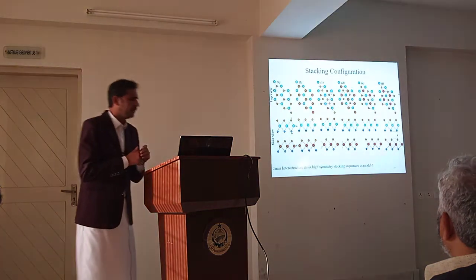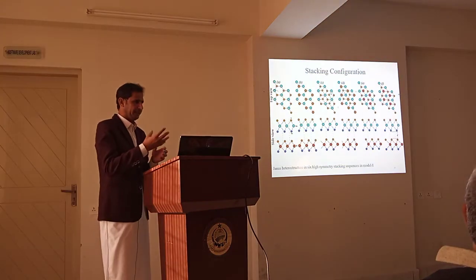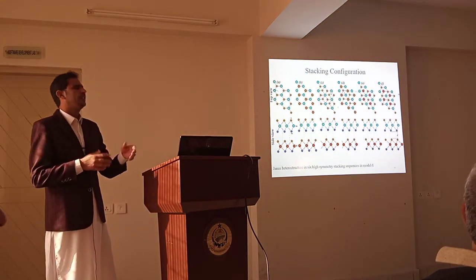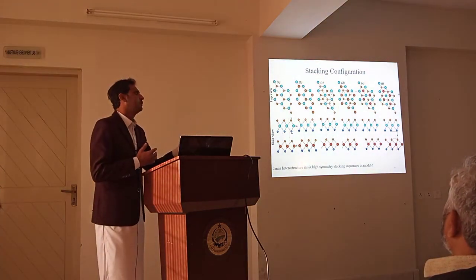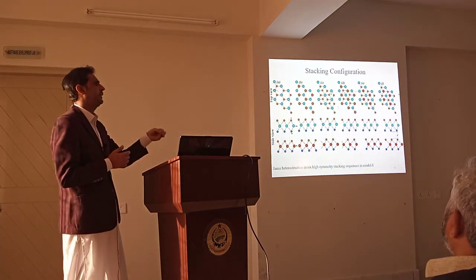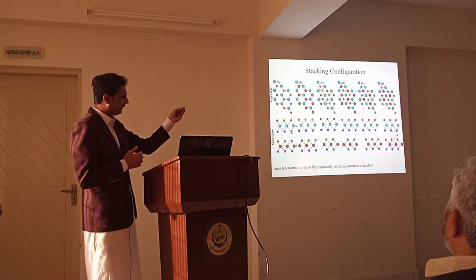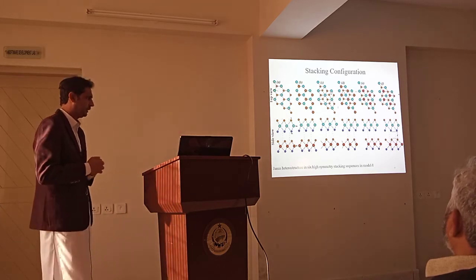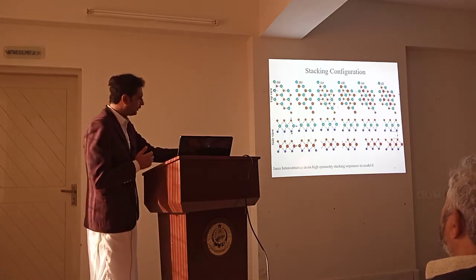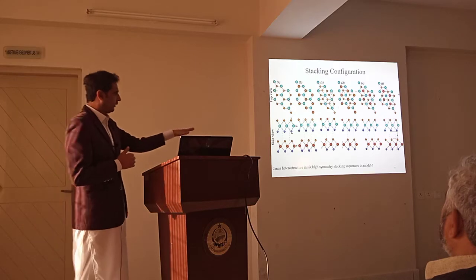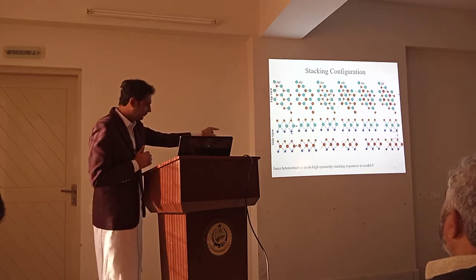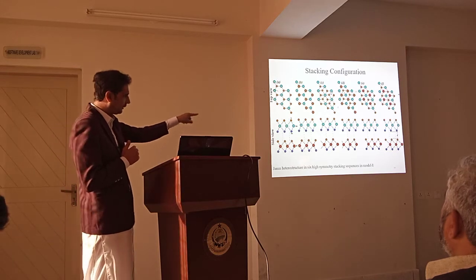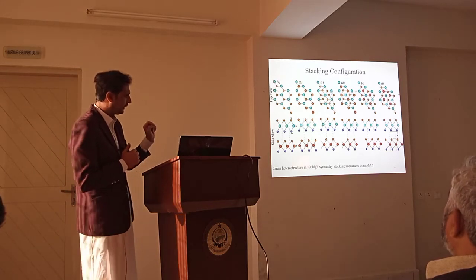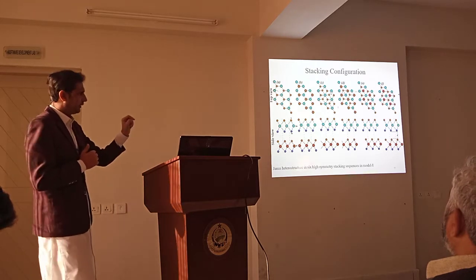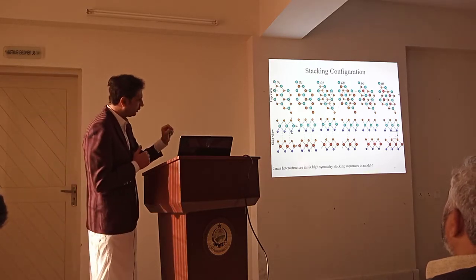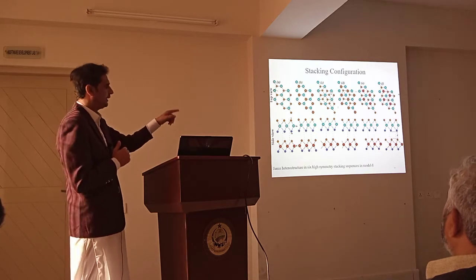By making the van der Waals heterostructure, we first check some configurations, because we know that electronic properties are sensitive to stacking. Here I represent six possible stacking configurations of Janus van der Waals heterostructures. In this figure I show the top view and side view. I am explaining it only from the side view because it is clear. In A, the transition metal atom is placed on top of the transition metal atom, while the chalcogen atom is placed on top of the chalcogen atom. In the second one, the transition metal atom is placed on top of the chalcogen atom, while the chalcogen atom is placed on the transition metal.